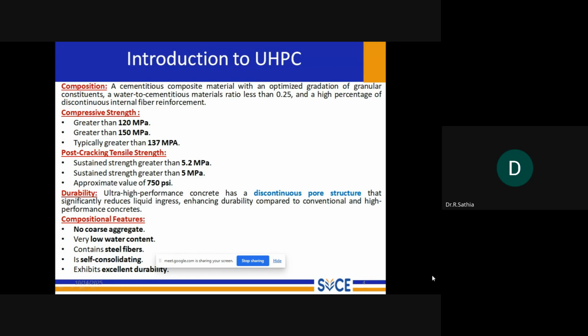So if you see, it is even more impressive to see the behavior after cracking. While normal concrete fails by brittle failure, this UHPC, that is ultra high performance concrete, maintains a good post-cracking tensile strength, sustained above 5.2 megapascal. It is those fibers, the steel fibers which you are adding, that bridge the micro cracks. So this is the fundamental shift in concrete behavior compared to your normal conventional concrete.